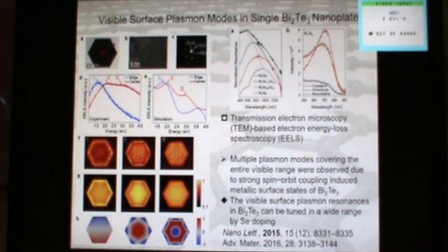And I think this kind of plasmon effect largely depends on the quality of the material. If you have a highly crystalline crystal, you have this peak. If you heat up the material to a certain temperature or use some other process to damage the crystal into amorphous or polycrystalline, the plasmon resonance will decrease. And if you use a chemical method to recrystallize the crystal, this can recover the plasmon resonance. That is quite interesting evidence that the plasmon depends on the crystallinity of the material.